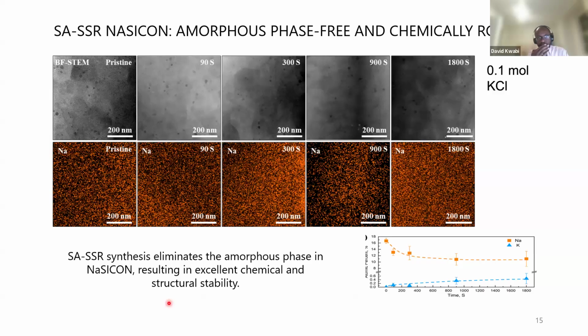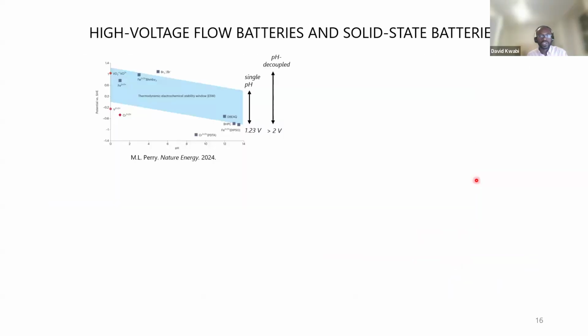And this is more TEM or electron microscopy data showing that, again, upon immersion in various electrolytes, in this case in 0.1 molar KCl, we have fairly robust stability. So what we're now doing with these membranes is putting them into redox flow batteries. And one of the goals, of course, is to prevent crossover, like I said, and bring about better capacity retention than we would have with a conventional polymer membrane.